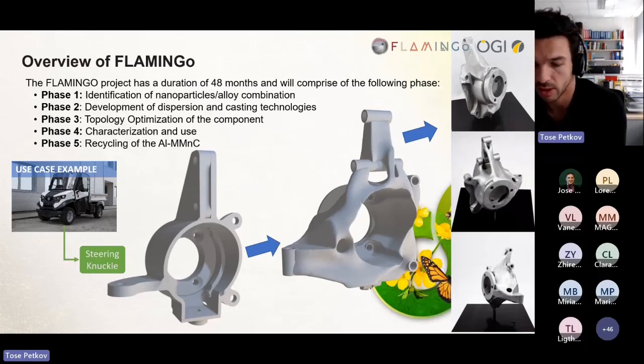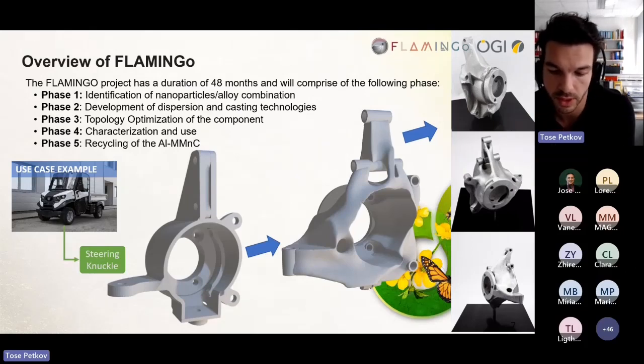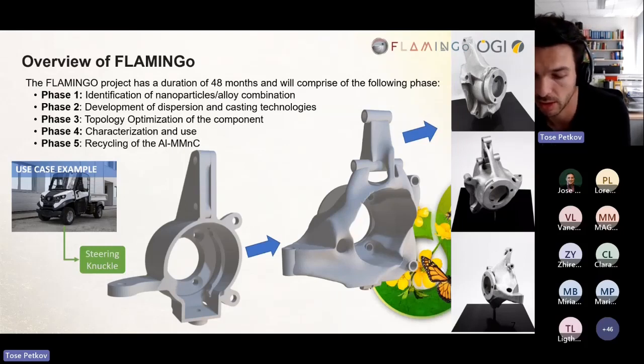The following five phases are included during the project. In the first phase, the identification of the nanoparticles and alloy combinations was carried out to ensure best results. Then the development of dispersion and casting technologies; ultrasonic and different stirring methods were used to ensure a homogeneous distribution. In the third phase, the topology optimization was performed with properties of nanoparticle reinforced aluminium by finite element methods. And in the fourth phase, the characterization by non-destructive testing and destructive testing. And the last part, recycling, to ensure circularity and environmental sustainability.